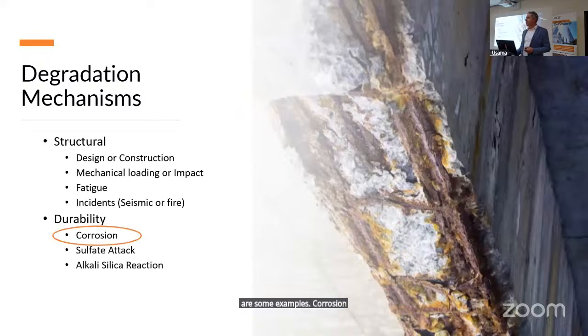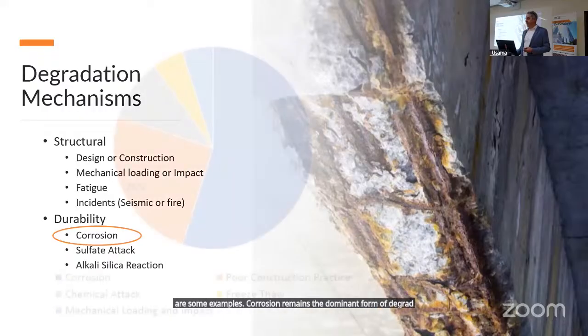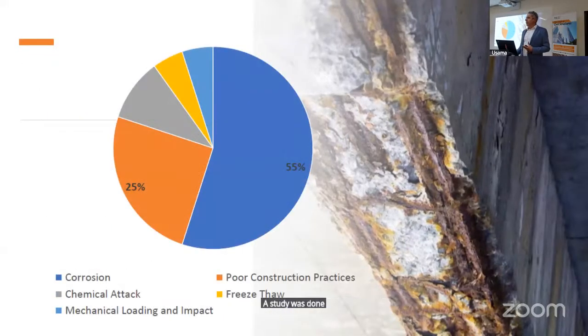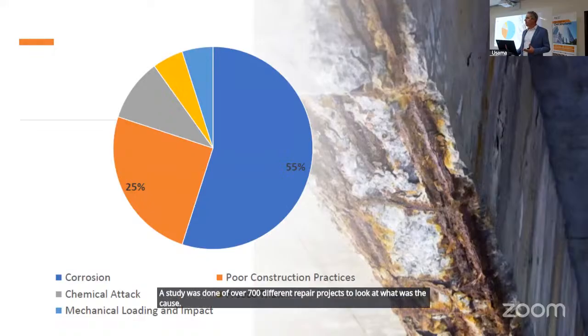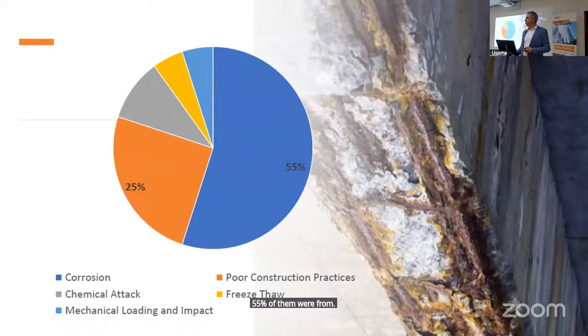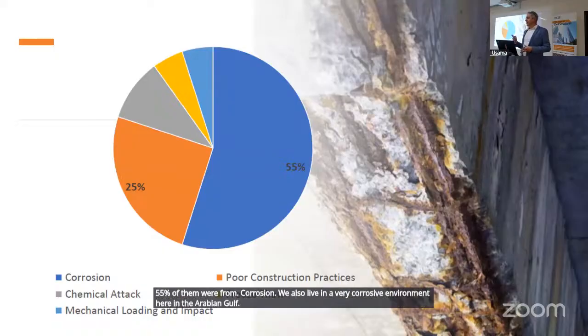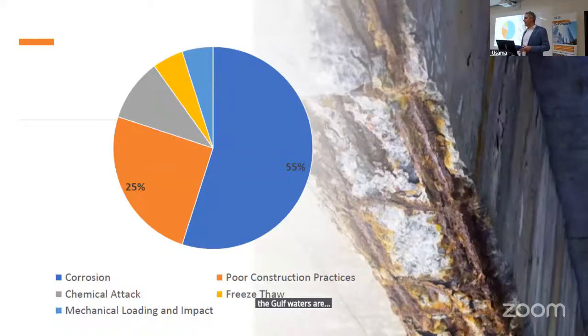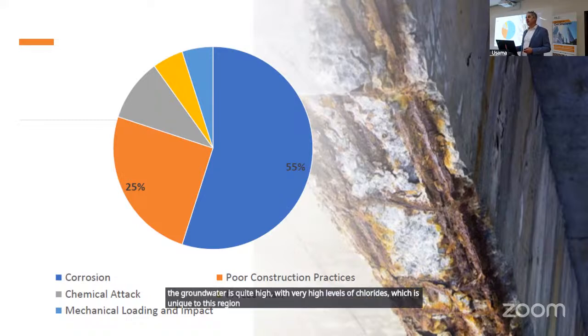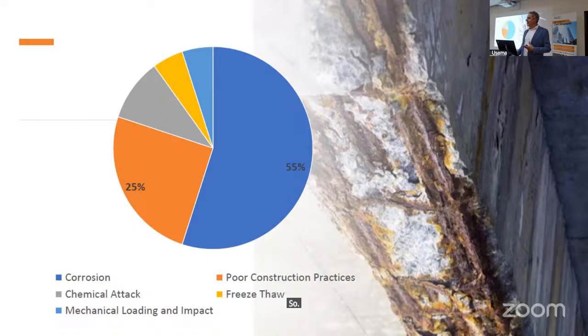Corrosion remains the dominant form of degradation. A study was done of over 700 different repair projects to look at what the cause was. 55% of them were from corrosion. We also live in a very corrosive environment here in the Arabian Gulf. The Gulf waters are only second to the Dead Sea from a salinity perspective. The groundwater is quite high, with very high levels of chlorides, which is unique to this region, causing high risk specifically for the substructures. So corrosion definitely is an area of